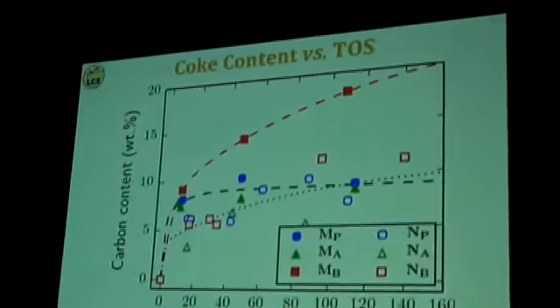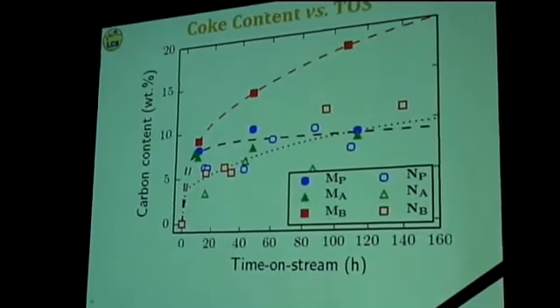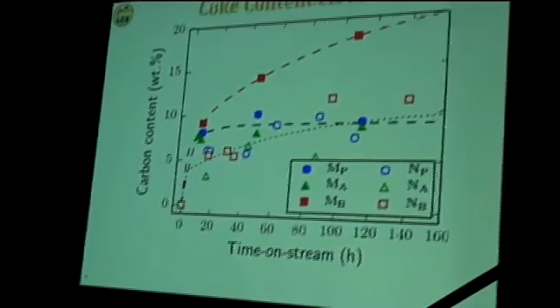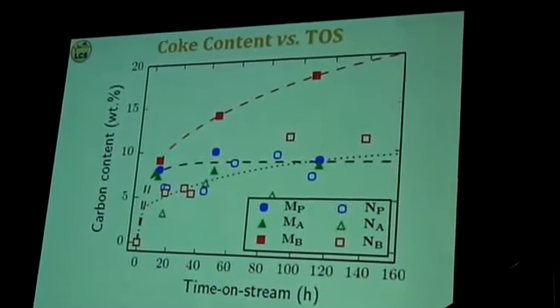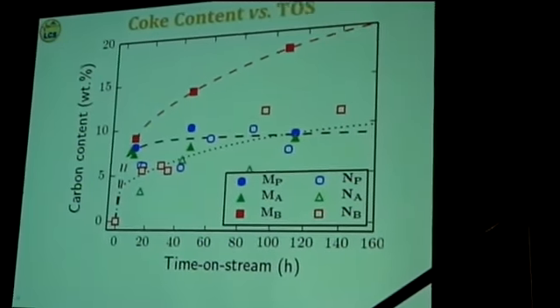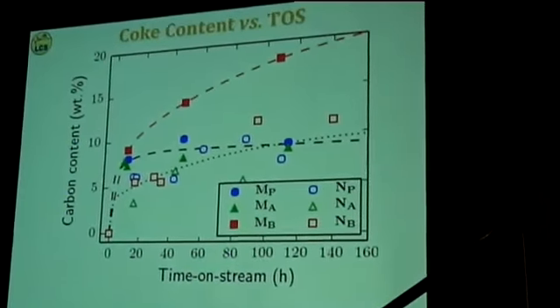What you see is that most of the catalyst, with the exception of the micron-sized crystal that has been treated with caustic, so that contains mesopores, have about the same level of coke. We are just leveling around 10% of coke, while this one is going way up.